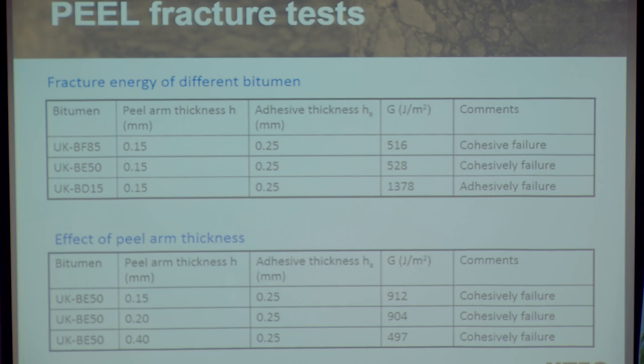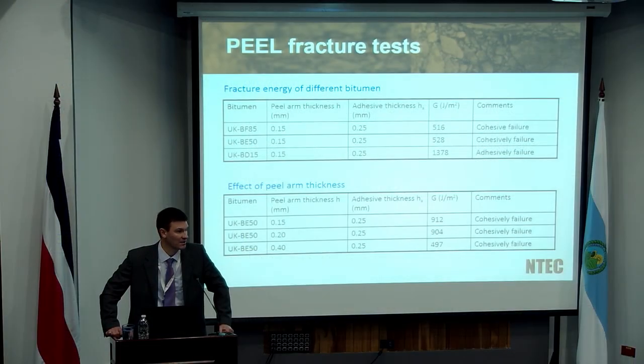So all the testing I'm going to show you from now onwards will be done with the 200 micron aluminium plate thickness. Just quickly, the top graph shows you those different types of softness or hardness of bitumen. I've showed you the 15 pen and the 85 pen. We also did a 50 pen. There are subtle differences. What tends to be the norm is that the stiffer the material, the higher its cohesive strength. And if failure is cohesive in nature, you will find that your harder binders will tend to give you a higher cohesive strength and therefore a higher peel strength.